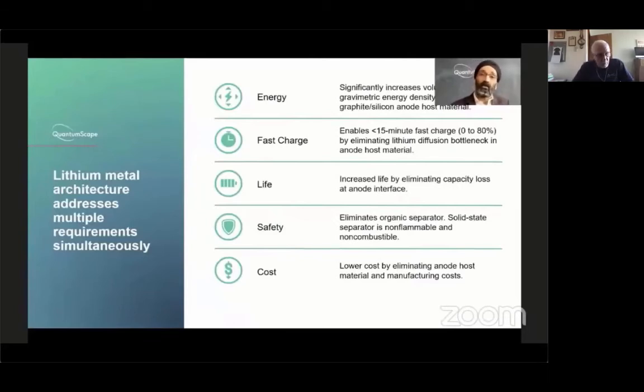You also solve or address the cycle life issue because it turns out that the cycle life is partly limited in conventional batteries by a side reaction that occurs between that liquid and the carbon particle. And by limiting the carbon particle, you eliminate that side reaction and therefore get better life performance. You improve the safety of the cell because the porous polymer separator is organic and is a fuel. It can melt at less than 200 degrees and then actually is a fuel that can burn. The ceramic solid state separator is already oxidized, so it's non-flammable, non-combustible, and it's stable to north of 1,000 degrees, which means that it actually can act as a fire break in the event of an adverse development.